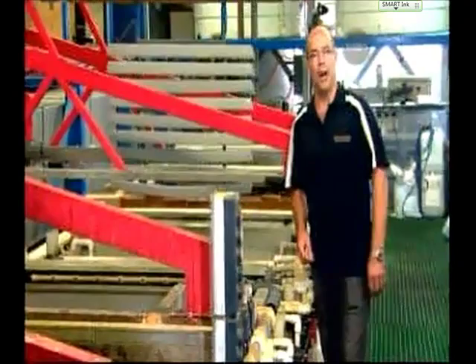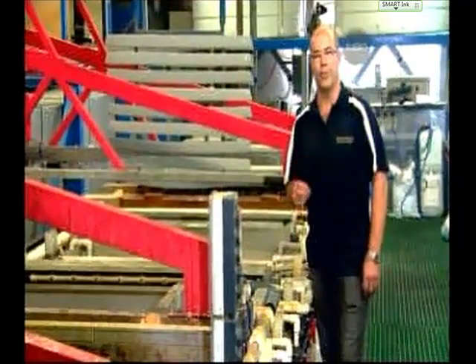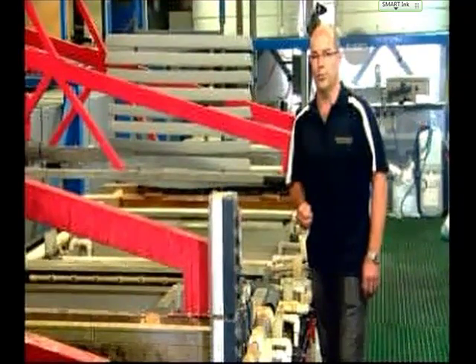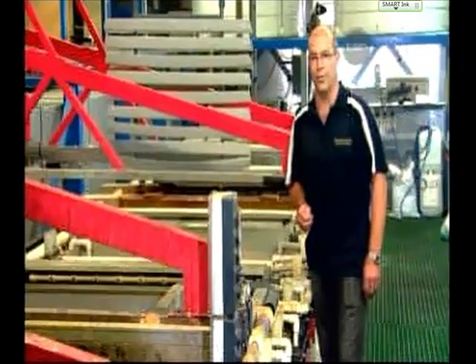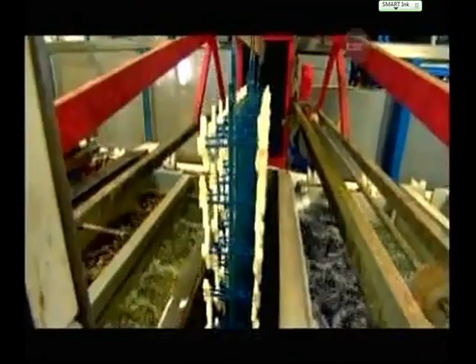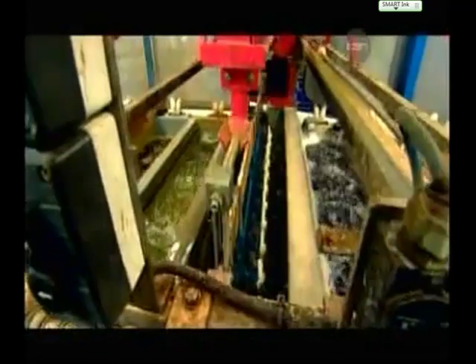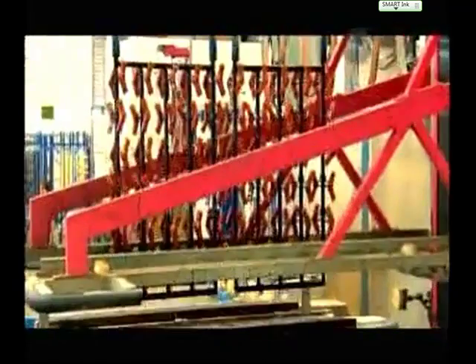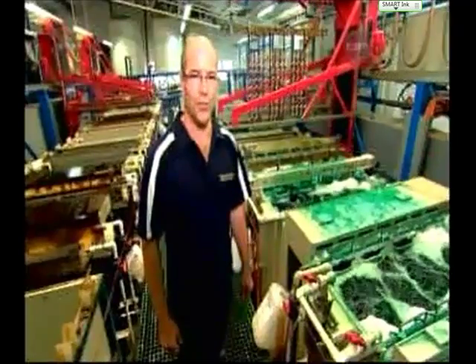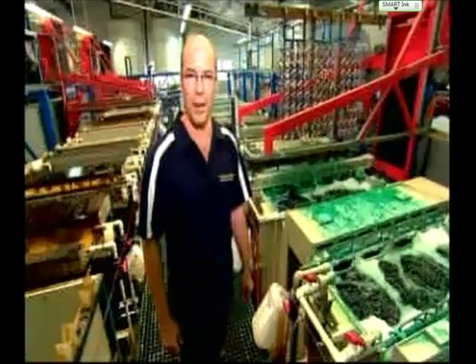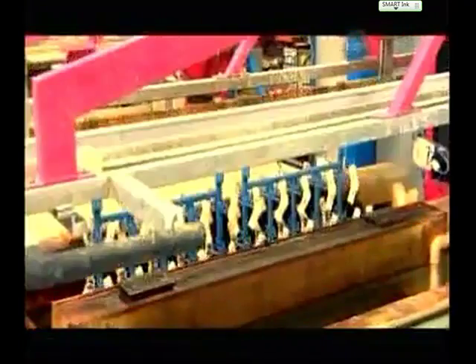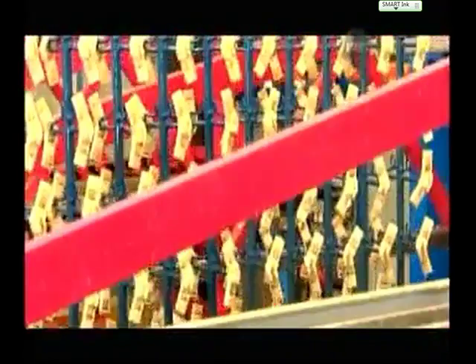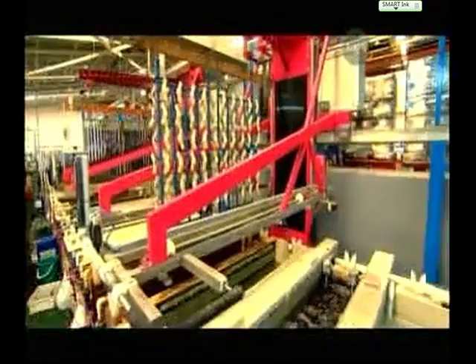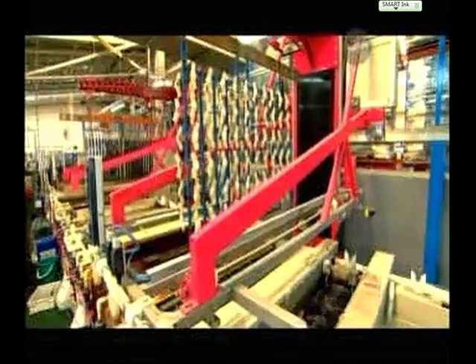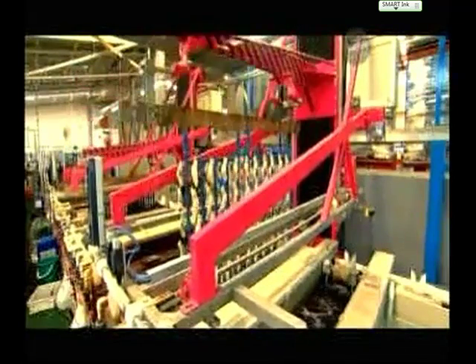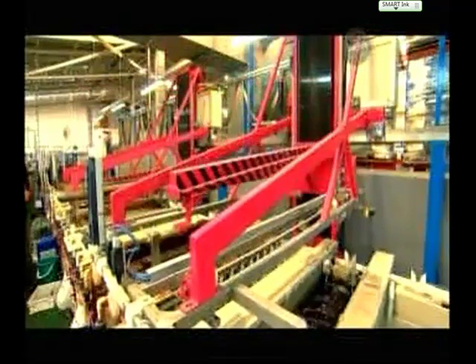To pre-treat plastic parts, we first have to process them through 4 different solutions. Each of these solutions will treat the surface in a different way without the use of electricity. The first solution is acidic. It etches the plastic so the layers we add on top afterwards will bind to it properly. The second and third solutions give the plastic parts an even coating of atoms of the metal palladium. And these allow the final pre-treatment layer of electroless nickel to grow on top. The metal-coated plastic parts can now conduct electricity and be electroplated in the same way as metal parts.